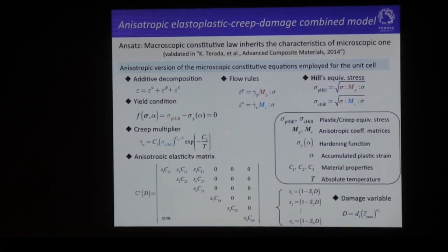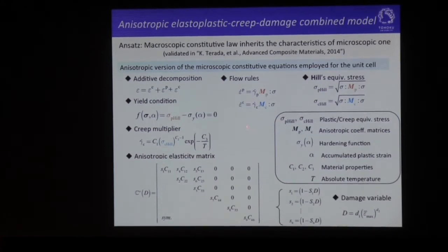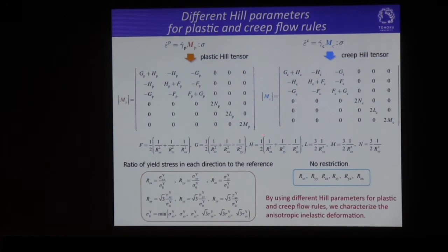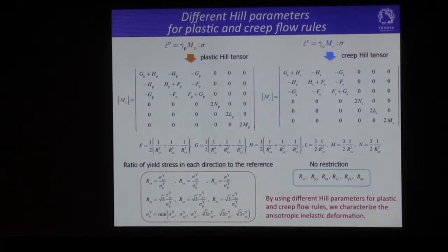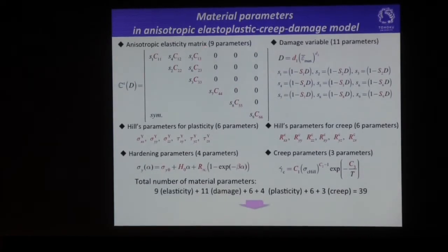These equations are almost the same as the equation assumed in the microscale, except for the anisotropy that can be represented by the Hill parameters in creep and plastic strain. So by using the different Hill parameters in plastic and creep flow rules, we can characterize the anisotropic inelastic deformation in this material. So these are the material parameters to be identified in this model. This model has 39 parameters. So we have to apply some sort of optimization method to identify these parameters.